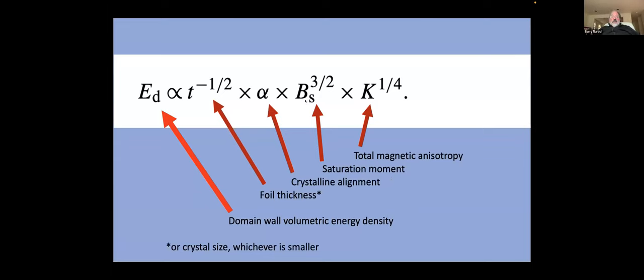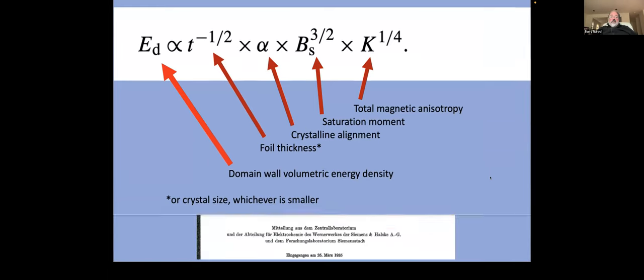The last two parameters: BS is the saturation moment. For quite a long time now, the community has known that if you can reduce the saturation moment, you can reduce the noise. And the last term here is the total magnetic anisotropy, which reflects in parameters such as initial permeability or coercivity. If you can get those numbers better, you get lower noise as well. And that's been also known for a long time. So this is the control over everything in regards to designing an instrument to get to lower noise.